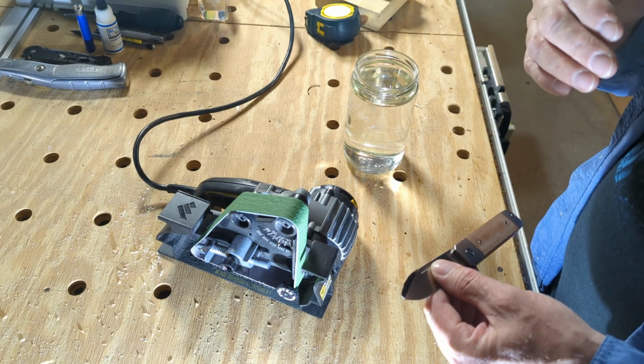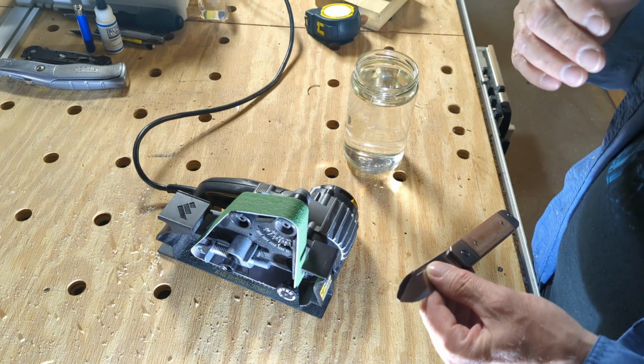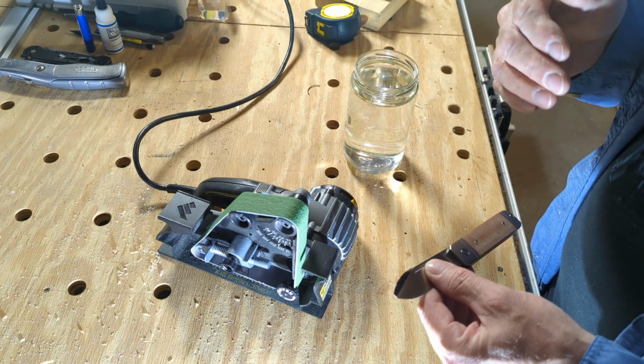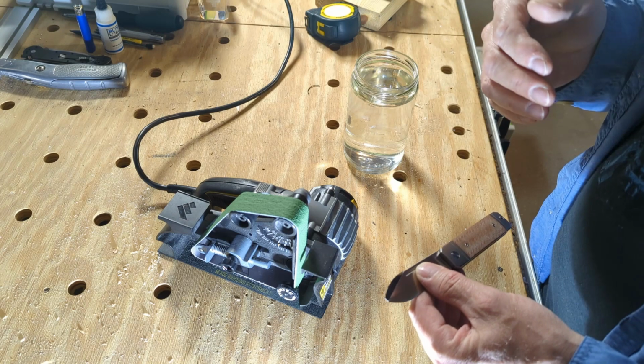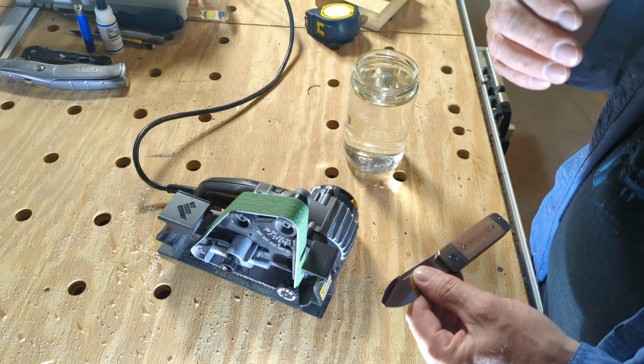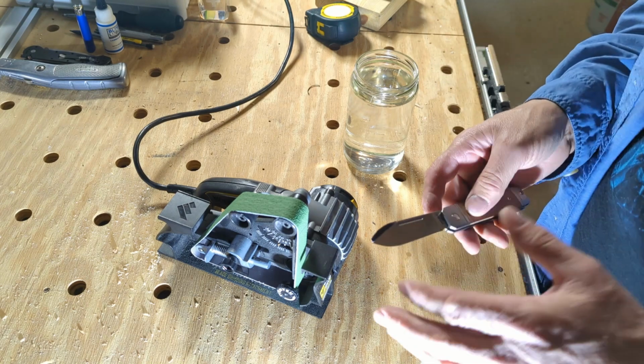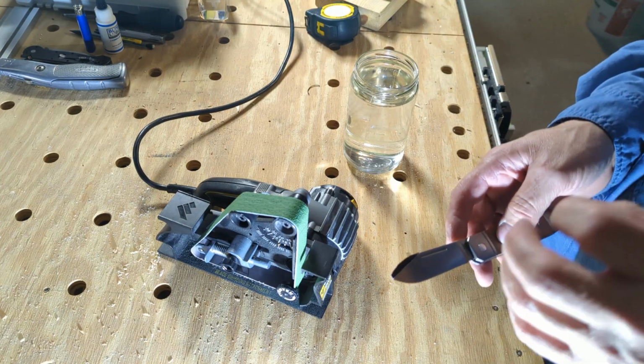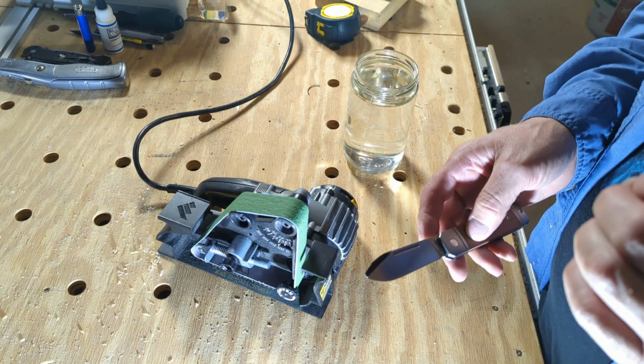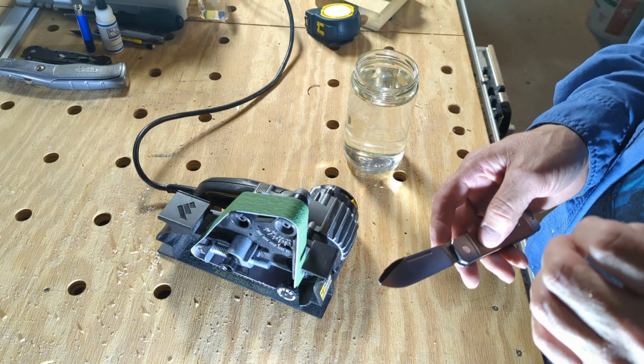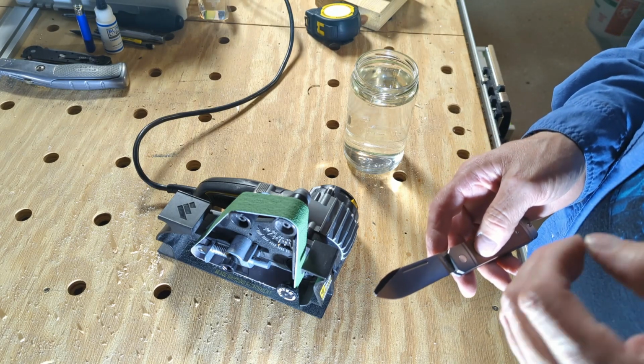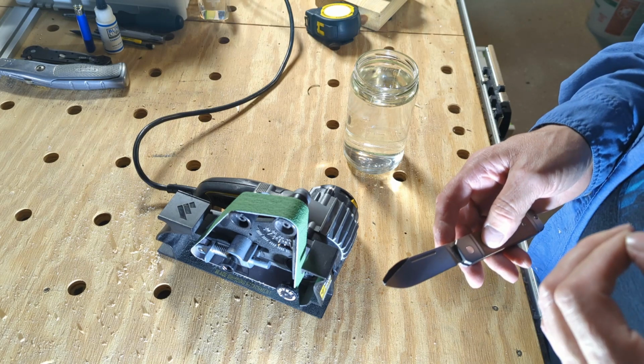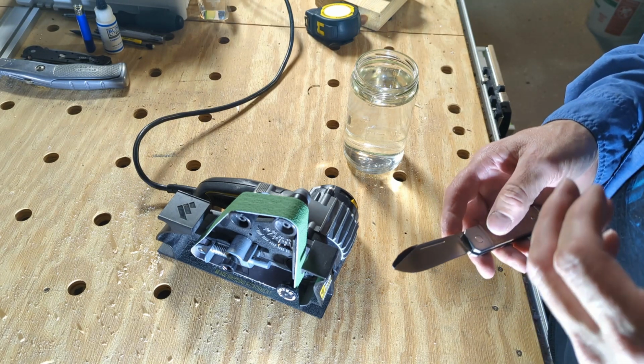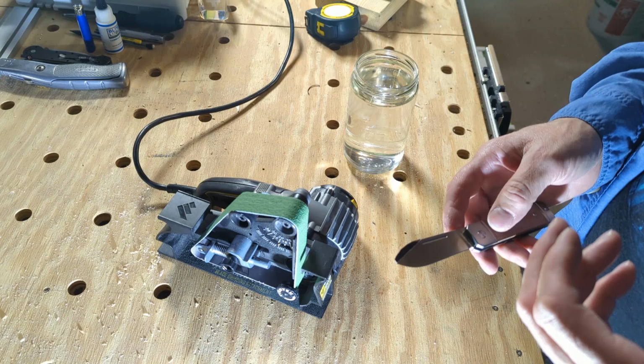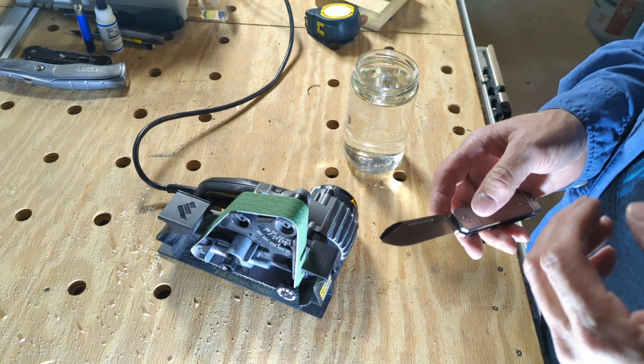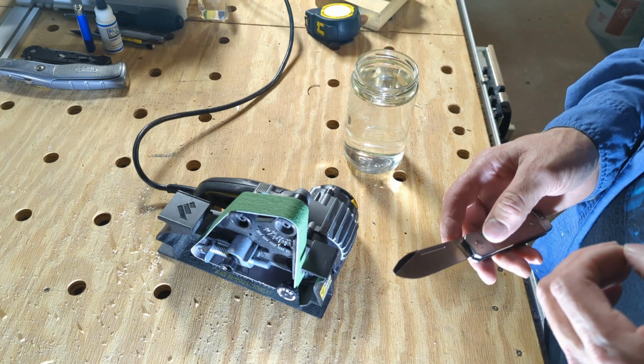You have to put it back in the oven at a much lower temperature. See, in the heat treating process, in the first step, you want the steel to reach its full potential hardness. And then in the tempering process, you want to bring it back to a usable hardness. You have to reach the full hardness in order for the molecular transformation to be complete in the steel and have the best possible blade. But at that extreme level of hardness, the steel will be too brittle. So we have to pull back the hardness. Now, for example, on carbon steels, I'll use temperatures around 350 to 500 degrees to do that. So you don't have to get that hot in order to ruin the heat treat.